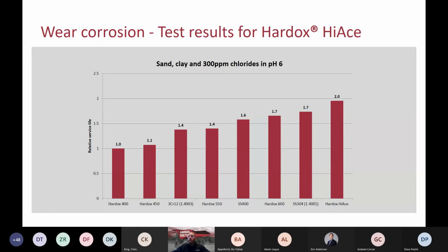And what we have seen with Hardox HiAce is about double the life over Hardox or AR 400 for something that has around 300 ppm of chlorides and about a pH of 6. We've actually seen better wear life out of the Hardox HiAce compared to some stainless steels, where you see the corrosion plus the abrasive wear. So this is not strictly a corrosive environment. You're actually seeing the corrosion plus the wear.